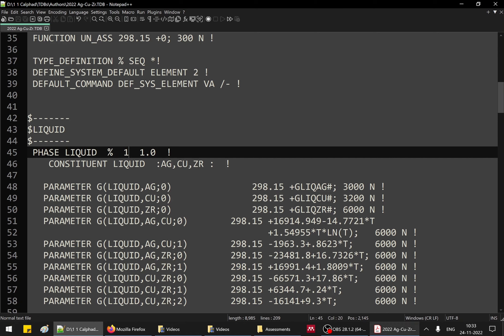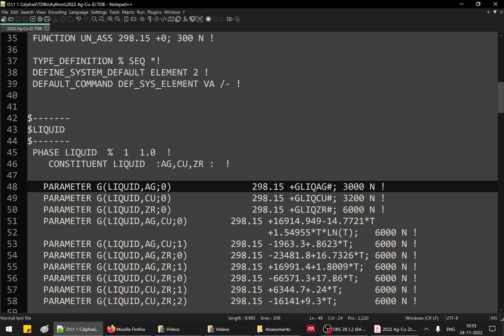Referring to the publication, you can see the phase models listing silver, copper, and zirconium in one single sub-lattice with occupancy 1. This is described in the TDB file accordingly. For the Gibbs energy of liquid silver, since it is already described as a function, only a call to that function needs to be entered here. Similarly, descriptions for copper and zirconium in the liquid state are entered by calling their respective functions.